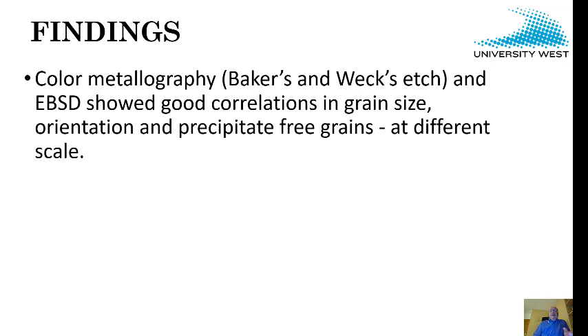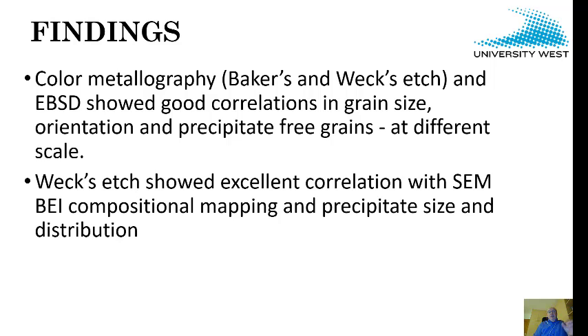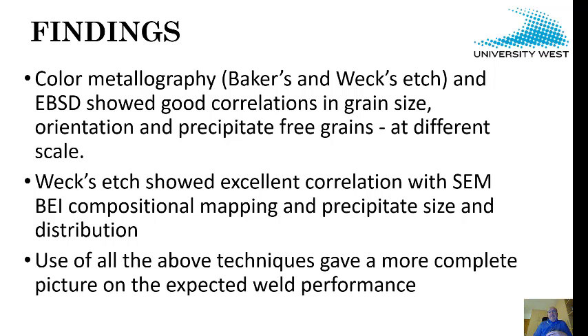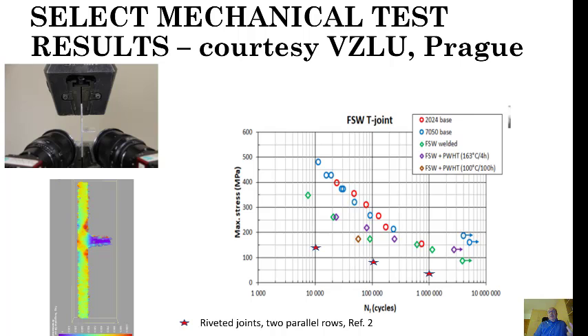And so overall, we found that color metallography showed a very good correlation with EBSD, but at a different scale. Yet it's much cheaper to do color metallography than EBSD. So you can save money by doing EBSD only on the areas of interest instead of just doing it at random everywhere. Then the other surprise was that Weck's etch showed such good correlation with compositional mapping that it's amazing. You can use it almost as a backscattered electron image map of different compositions, in this case zinc-rich and copper-rich regions. And then all these techniques gave us a more complete picture of the weld performance.